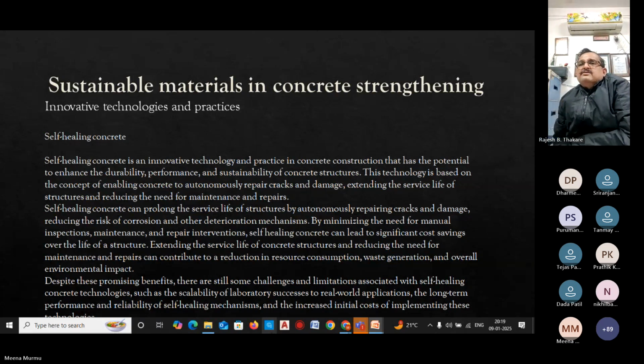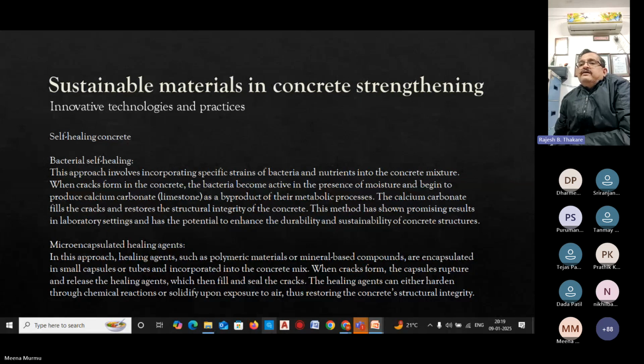strengthening of the concrete. So the second method is micro and macro encapsulated healing agents, which can be encapsulated in a polymeric material or a mineral-based compound, in a small capsule or tubes, or incorporated into the designed concrete mix. When cracks are formed, the capsule ruptures and releases the healing agent, which can then fill and seal the crack. The healing agent can either harden through a chemical reaction or solidify upon exposure to air, thus restoring the concrete's structural integrity.